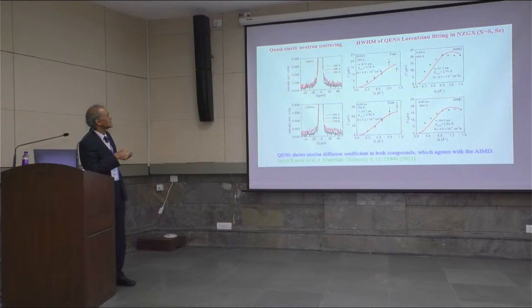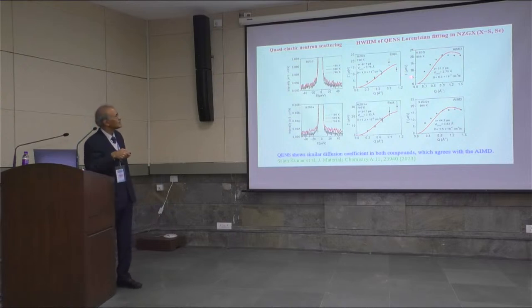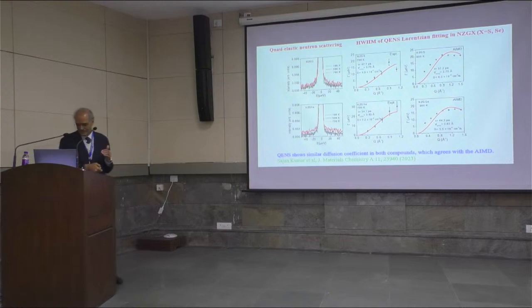The other kind of measurement, quasi-elastic neutron scattering, we do see the broadening as a function of temperature. Then again, the broadening of the elastic line as a function of momentum transfer is plotted. This is experimental data from the national laboratory. We can also see the corresponding calculations from the molecular dynamics simulation. So this essentially helps in validating the simulations, and then we use simulations for a more detailed understanding of the underlying microscopic physics.